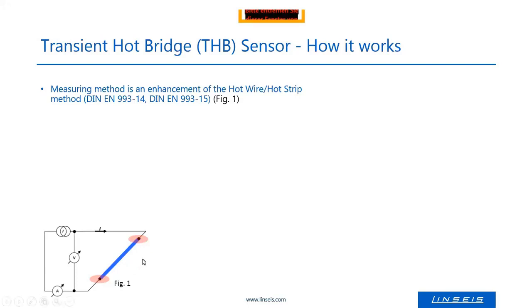The disadvantage of these old hot wire methods is that you have edge effects where the cables are welded or soldered. You are losing heat here, which leads to uncertainties. Then the overall resistance of such a wire is quite small, and the effect which you want to measure, the delta T or temperature increase, is very small, so you need sophisticated electronics with lock-in amplifiers and stuff like that. So it's challenging. The goal to develop the transient hot bridge method was to get rid of the disadvantages of the classical hot wire method. And there are some steps in the development